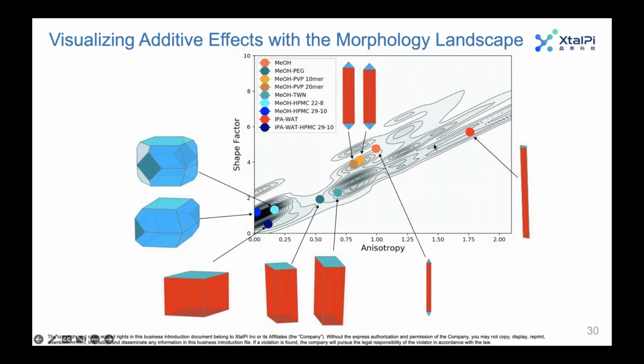So this again is the morphology landscape for metformin HCl, and we can plot the morphologies that we calculated under the different experimental conditions. The most needle-like morphologies are for the pure solvents. So we have IPA water over here, and then we have MEOH here. The next is PVP, where we saw that we obtained some fatter needle-like structures, but we didn't deviate away from needles altogether. Those are here clustered together.